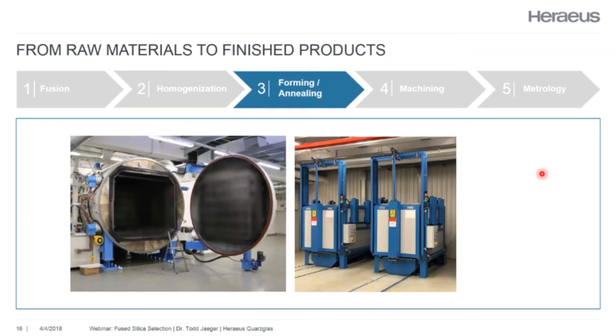The forming and annealing is a vital step. We can take the ingot that we form in the earlier processes that were mentioned and place a certain calculated mass within a carbon mold. The carbon mold then would go into the large forming furnace, be heated back up, and this would go through a reflow where we can make rectangular or round various sizes of ingot.